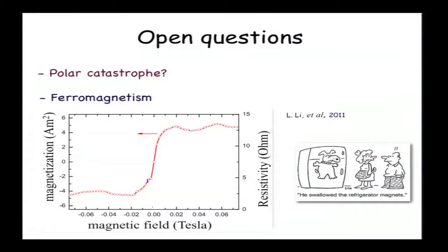Another open question is the origin of ferromagnetism in the system. This measurement was done by Lu Li, who is a former Pappalardo fellow, and was talking about that just last year. He was doing that in the lab of Ray Ashoori. He was measuring the magnetization as a function of magnetic field, obtaining a very large ferromagnetic moment in the system. And this ferromagnetism is actually going to remain at very high temperatures. He also measured, in the same system, again as a function of magnetic field, the resistivity. Starting from high magnetic field, he saw that there is almost no change in the resistivity when he is lowering the magnetic field. However, at a certain magnetic field, the resistivity goes down to zero, and the system becomes superconducting.